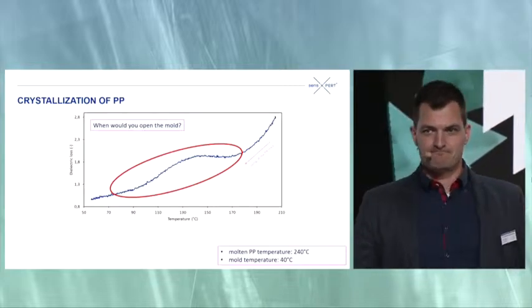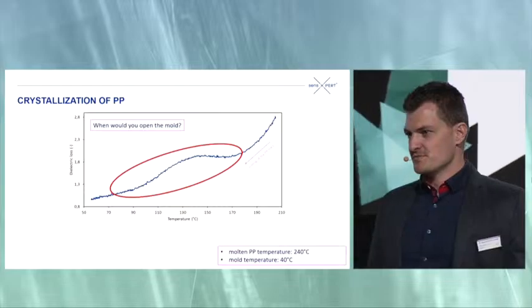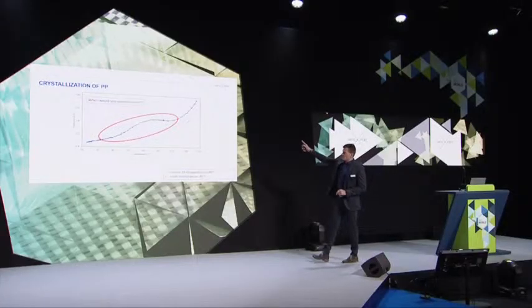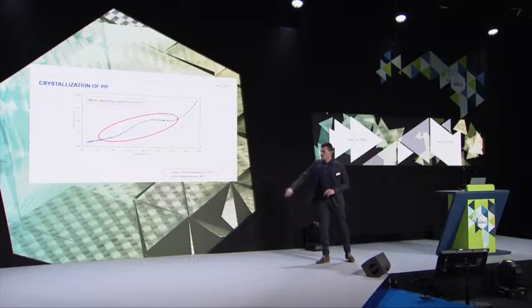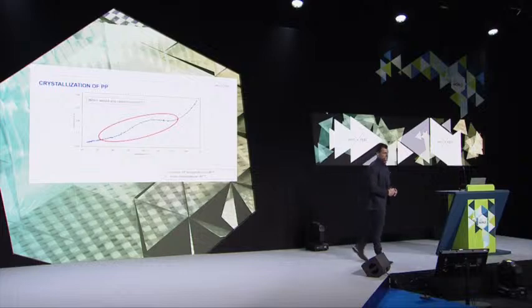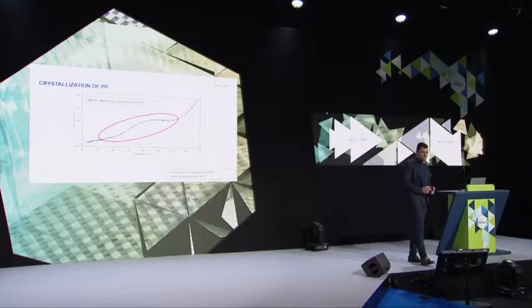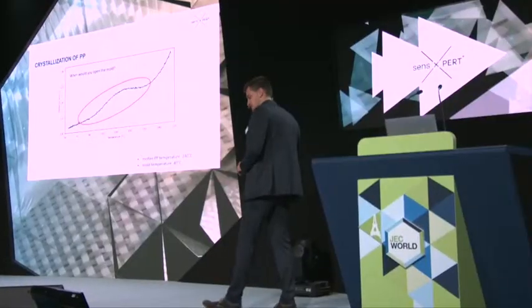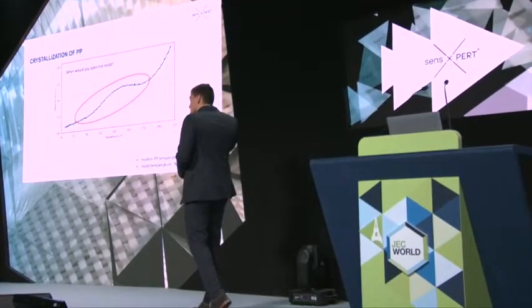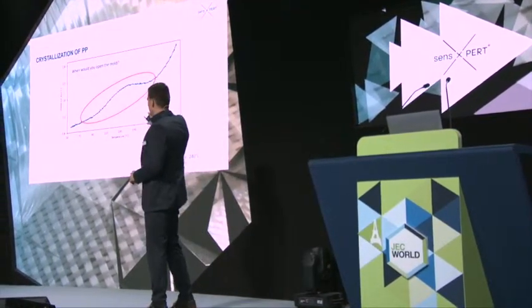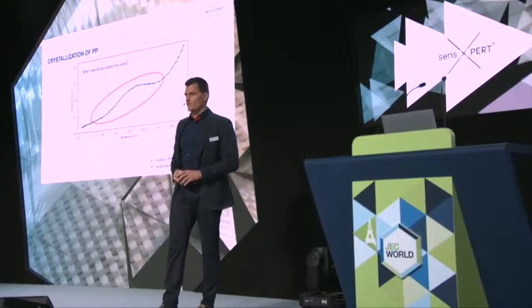Thermoplastics, warpage, stability in dimensions. These are the big topics here. Residual stresses. What you can see here is the cool down ramp of a thermoplastic material during molding. This is polypropylene in this case. Initial temperature in the molten state, 240 degrees C, mold temperature, 40 degrees C.